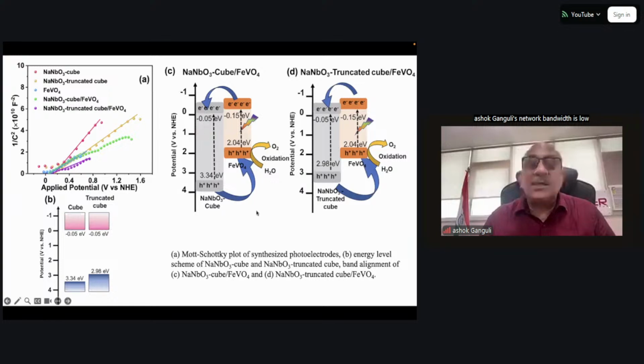And you can see that there is some change in this level. This is at 2.98 electron volts, whereas for the normal cube, it is at 3.34 electron volts. And these kind of changes make the transfer of electron and hole more efficient in the case where you have the iron vanadate on top of the truncated cube.